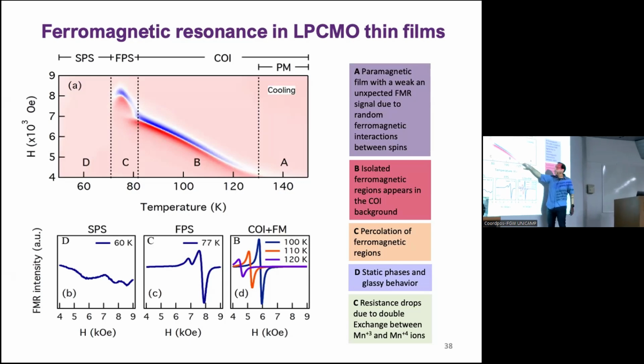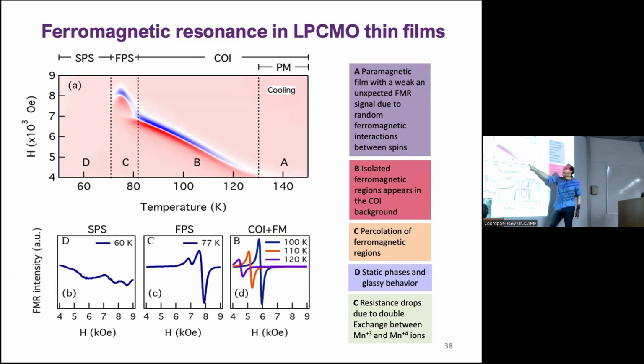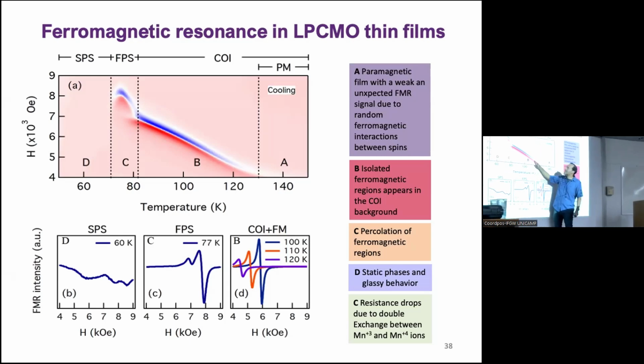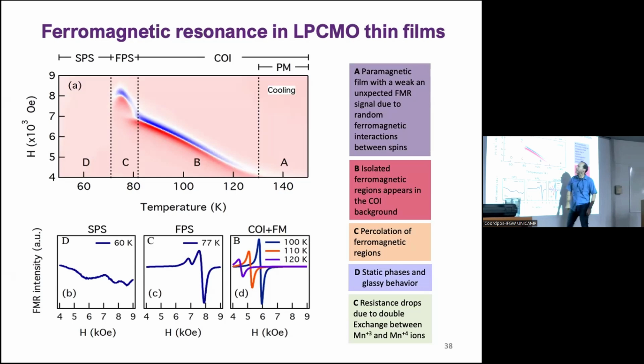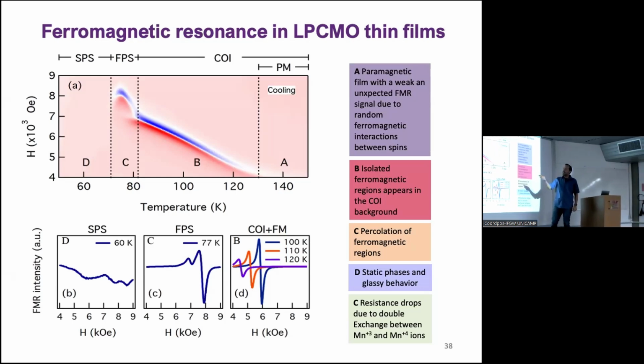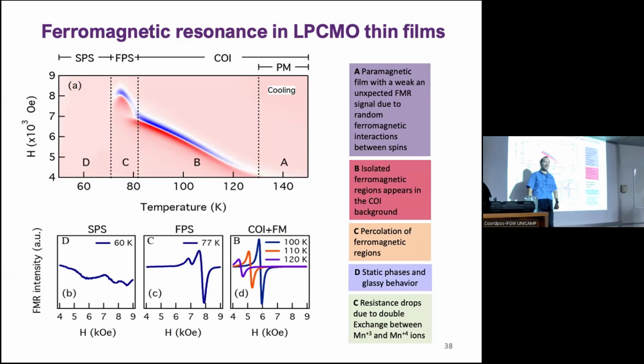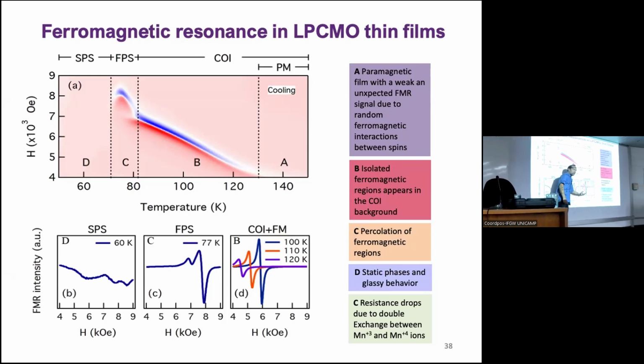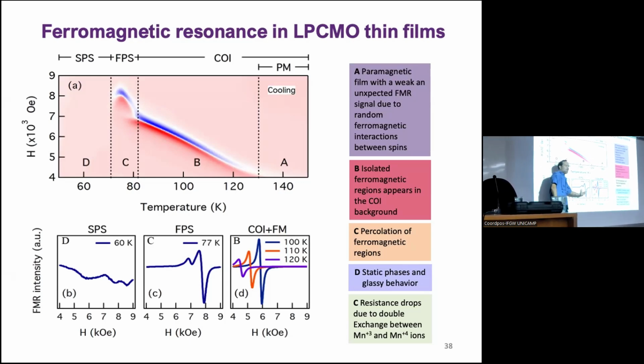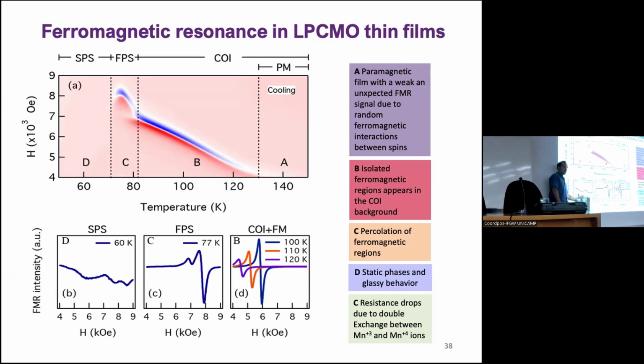Then it enters to a region where we are sensitive here just to the ferromagnetic effects, just to be clear. And then we see the kicking in of the ferromagnetic domains, and they start to grow, right? And then the resonance field gets higher, okay? And then at some point, it changes a lot. It changes the resonance field, it gets stronger, and then it disappears. There is no dynamics. And here is just a snapshot of every region. So here you have very beautiful resonances that change in resonance field. Here you have the coexistence of two domains. There is two domains here, 1 and 2, for instance. And then here, there is no coherent rotation. It's the same material, we are just changing the temperature.